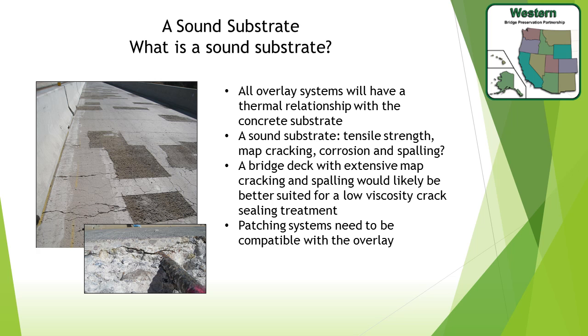When you talk about thin polymer overlay systems, you need to err on the conservative side. The state of Utah installs these on new decks. Spencer talked about why — after one year, here in Utah, you have enough chloride content at the top mat of reinforcing steel to have corrosion potential. So I think it's a good idea to install these things earlier rather than later.